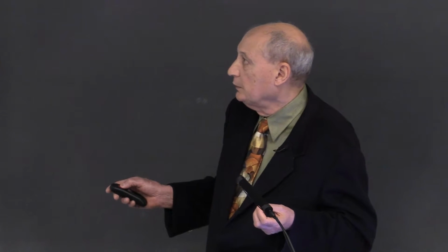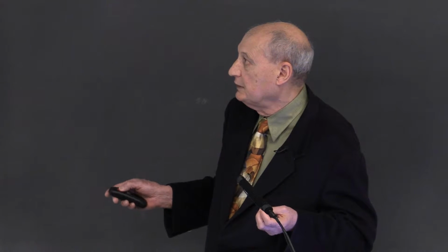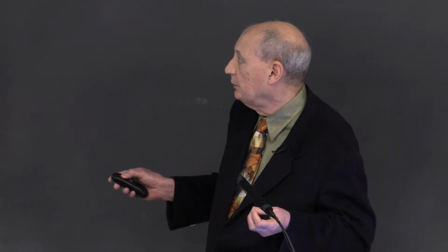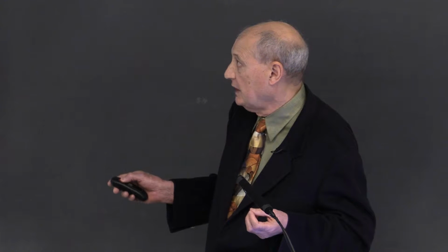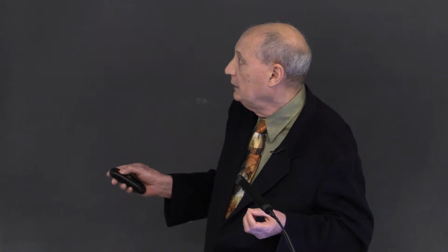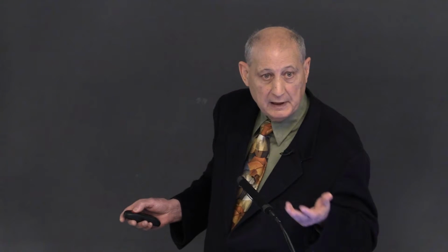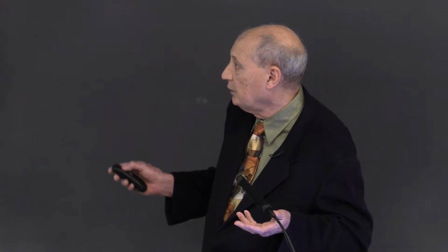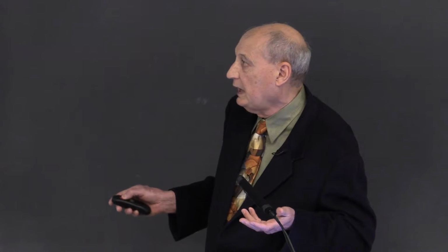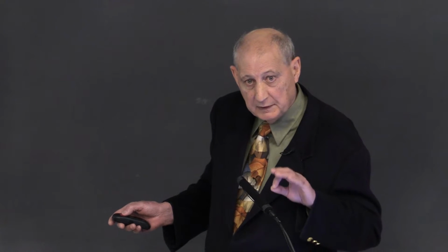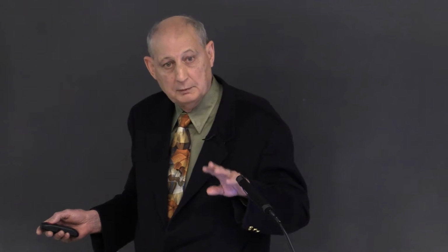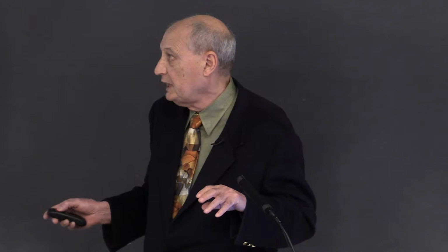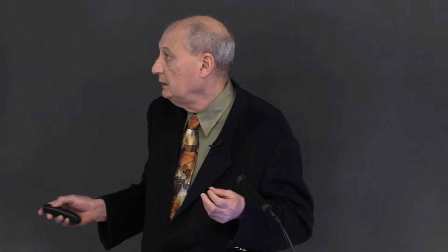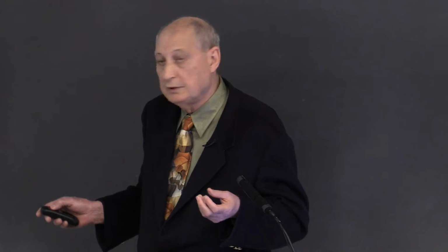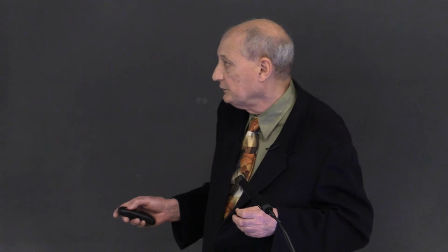But you would also note that in addition to considering these low number density materials which account for this level of improvement, since 2014 we've had a dramatic improvement in electro-optic activity by going to high number density materials. And this involves a dramatic complication of the system and an entirely expanded theoretical treatment, which we'll describe later on in this talk.